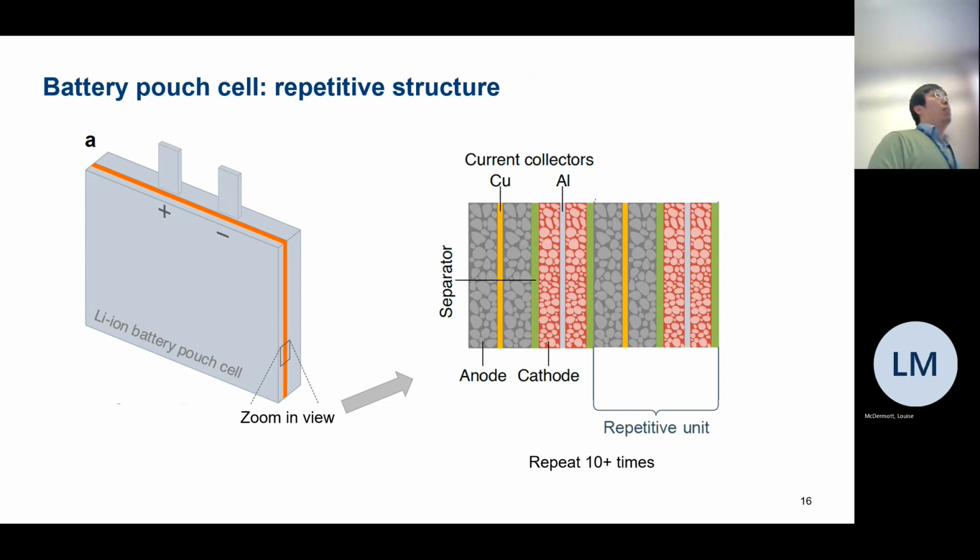So what we thought at the start of the project is, because you have this repetition pattern, if you put an ultrasonic wave through, and if the frequency is right, then the reflections from these layers will potentially form a resonance, because you have the same pattern of reflections overlapping with each other. That was the initial idea.